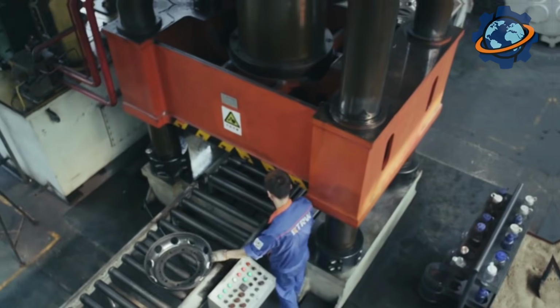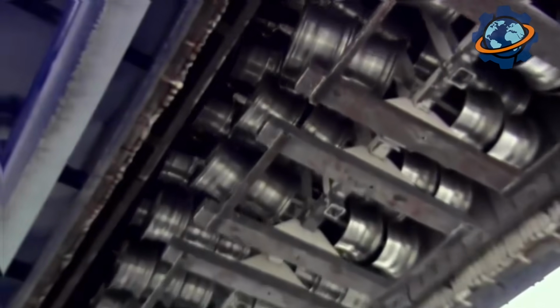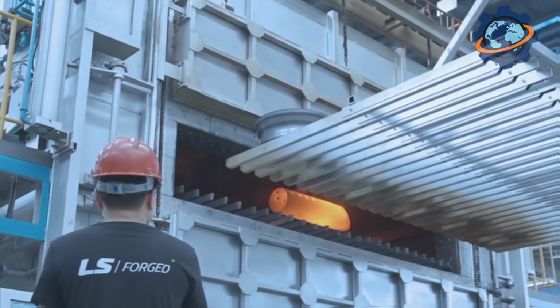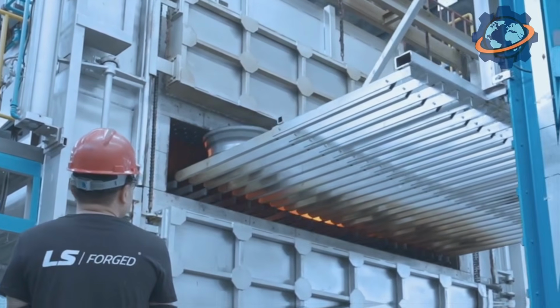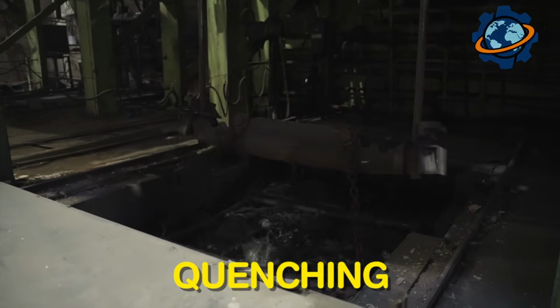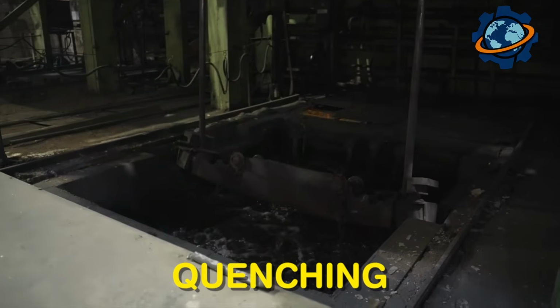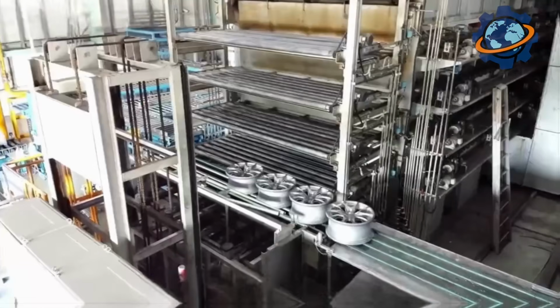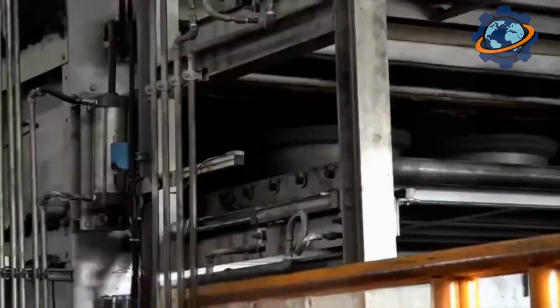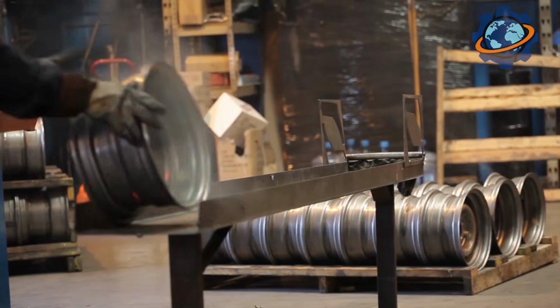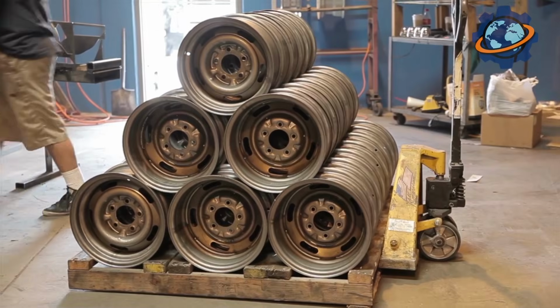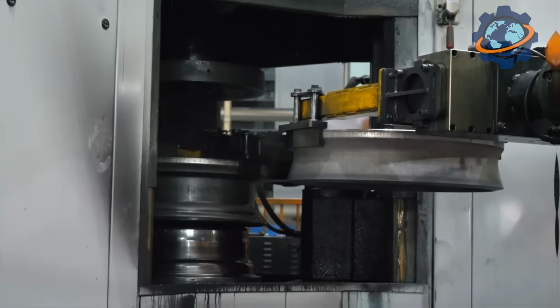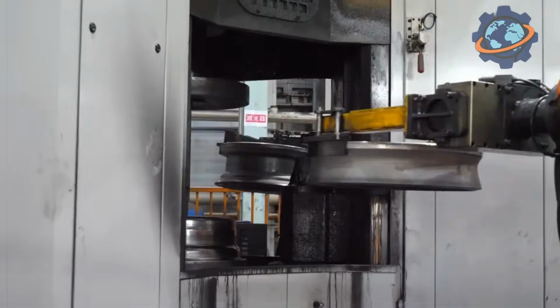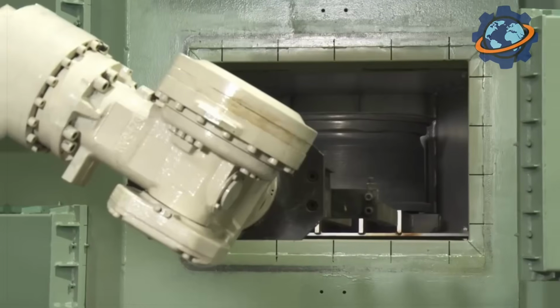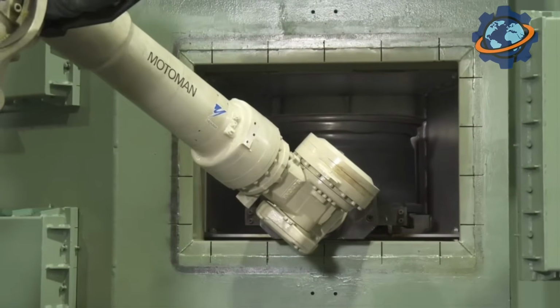Now comes heat treatment. This is a stage that's invisible but critically important. The workpiece is heated to a specific temperature, held there, then rapidly cooled in water. That's called quenching. Then comes aging, heating to a lower temperature, and a long hold. This entire sequence changes the alloy's microstructure at the molecular level. Magnesium and silicon atoms form tiny hard particles that strengthen the aluminum matrix. After heat treatment, the wheel can handle loads that would tear apart an untreated blank.